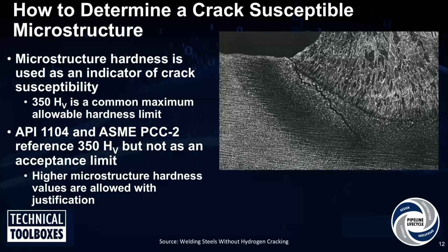And on the other side, if you make welds with cellulosic electrodes, which have a quite large amount of hydrogen, you would have welds that will have a hardness below 350, and those welds still might crack. Right? So there has been a lot of work in the last 10, 15 years really looking at what will be considered an acceptable hardness limit for in-service welds, and trying to get away from this idea that 350 Vickers hardness is the limit that we should live and die by.